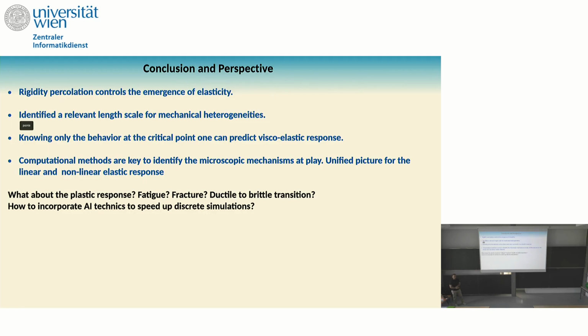So here, as I told you, rigidity percolation for the elasticity of this soft system is very important. By knowing what happened at the critical point, you can really predict the rheological properties, in the linear regime but also the viscoelastic properties. And all of them depend only on what happened at the critical point. The critical point is important. It's like the cosmic wave background: the properties of the cosmic wave background impact a lot what happens nowadays. It's the same for the rheology of this system. What happened at the rigidity percolation threshold is crucial to understand the linear and nonlinear behavior.